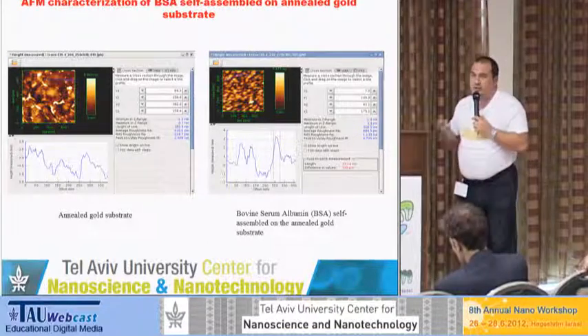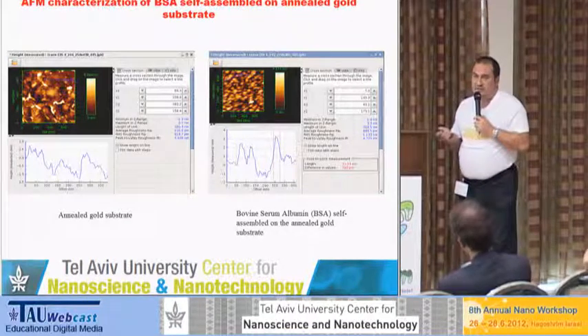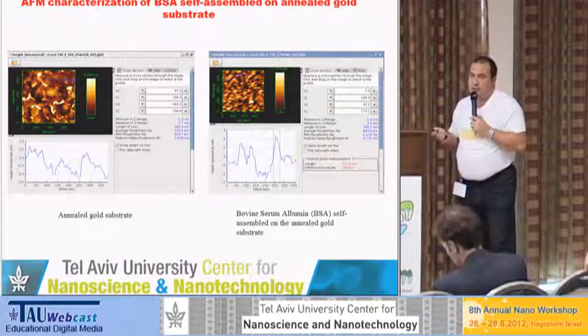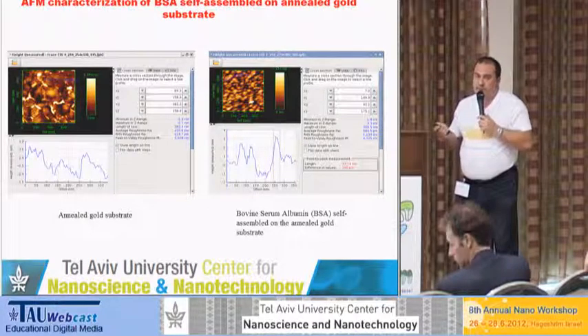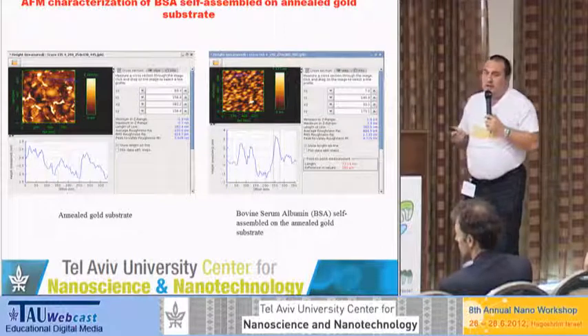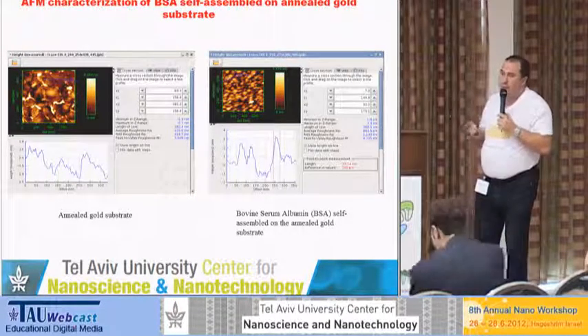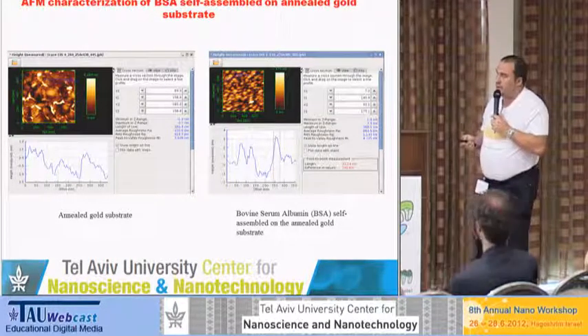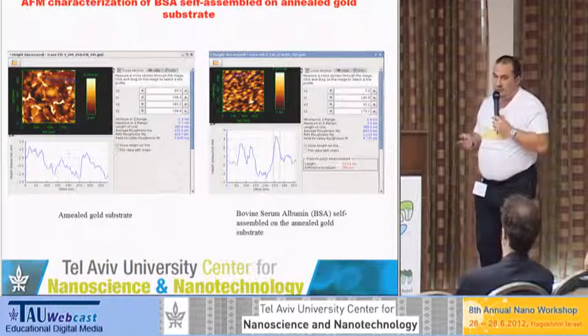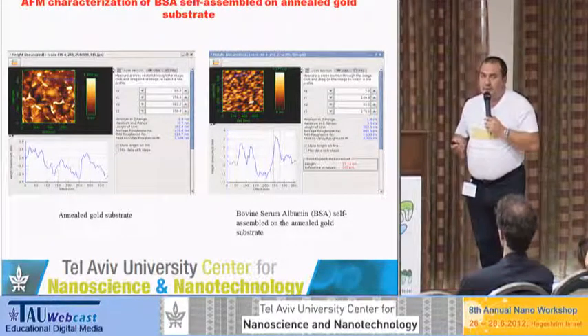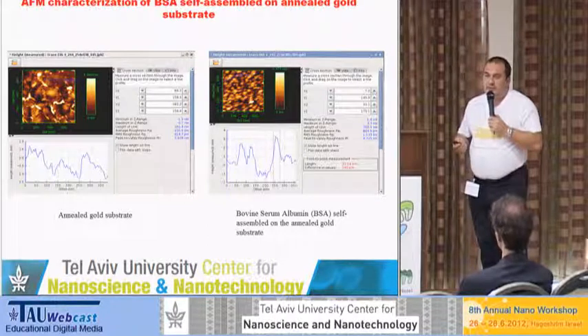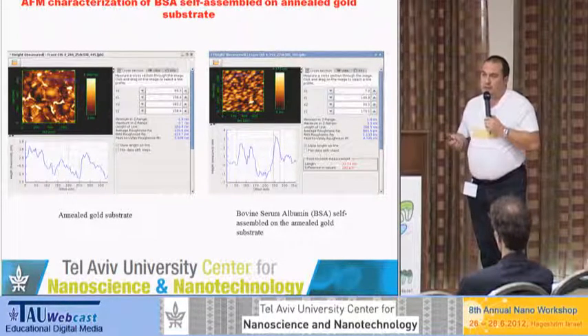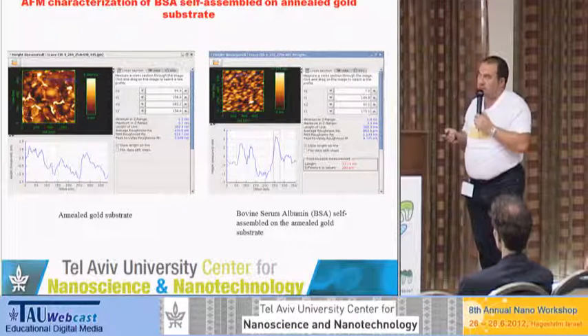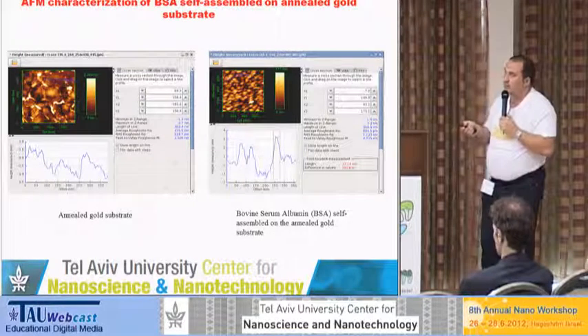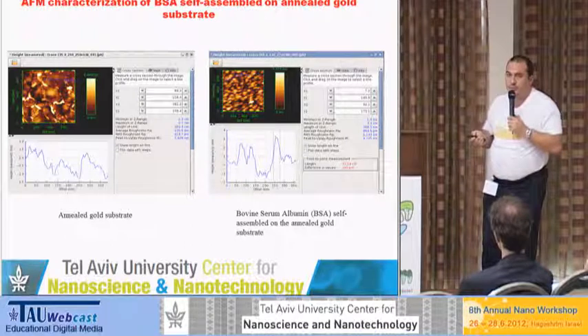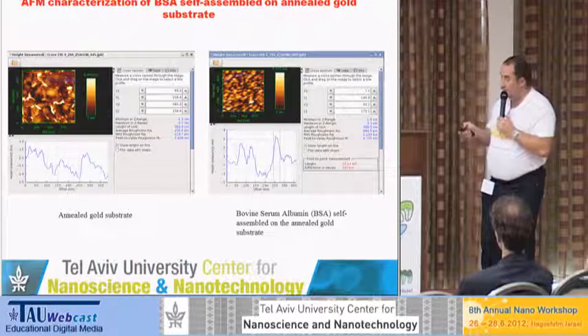And if you take into account that the tip itself is about 15-20 nanometer, and a single molecule of BSA is about probably 10 nanometer, rough order of magnitude, it could be that we see single molecules of BSA here. And of course, we need to continue with this research to make the annealed gold sample better and further find the optimal parameters for further characterization.